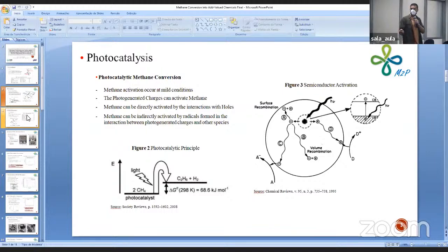We have then 4 major processes that can happen. We have processes A and B, representing the recombination of those charges at the surface or in the volume of the semiconductor, respectively. And more interesting, we have processes C and D, where these charges can travel to the surface of the semiconductor's particle and be free to react with species present in the system.